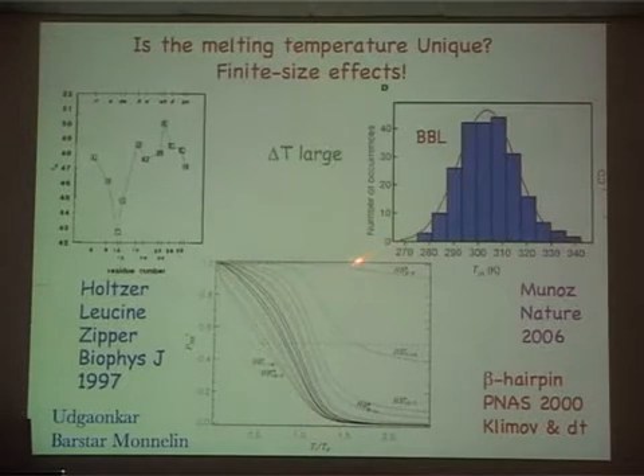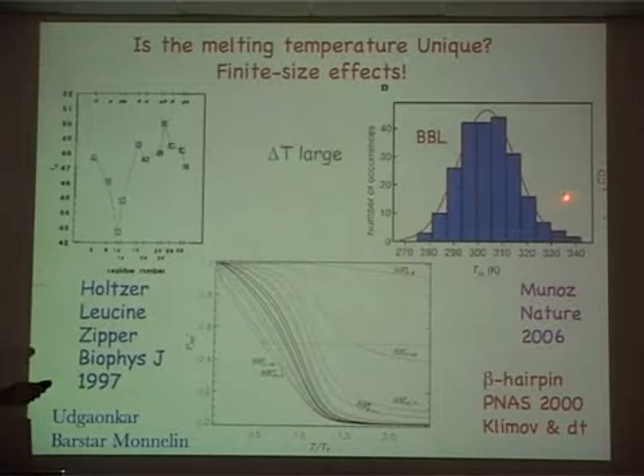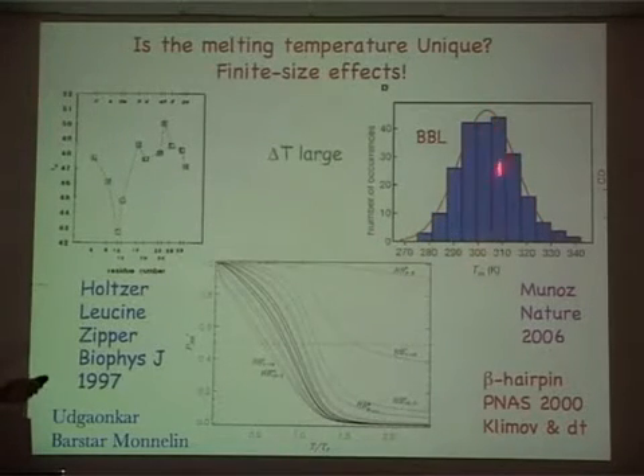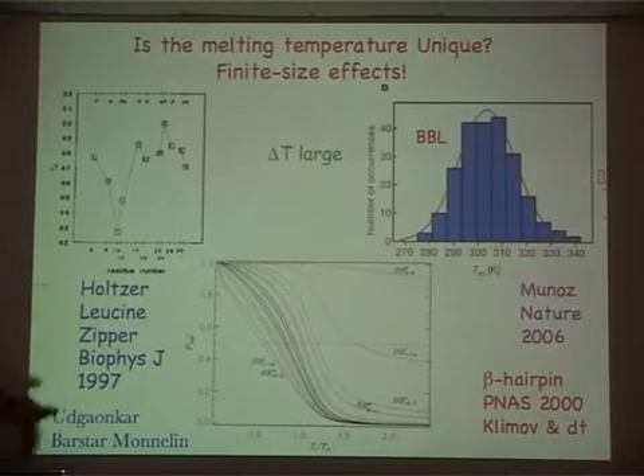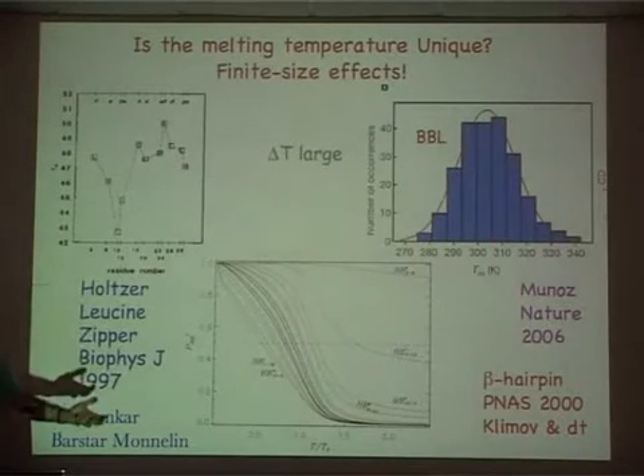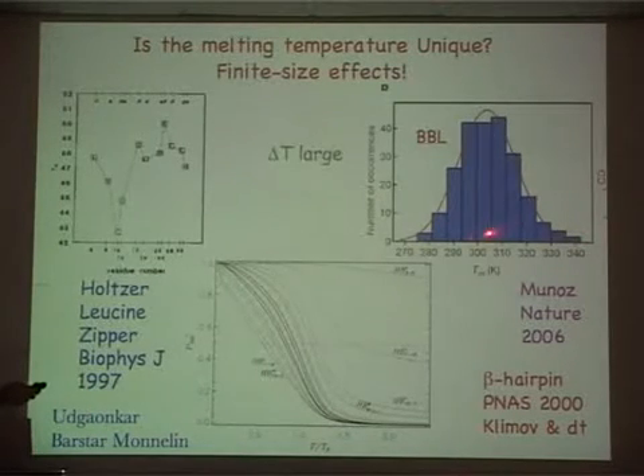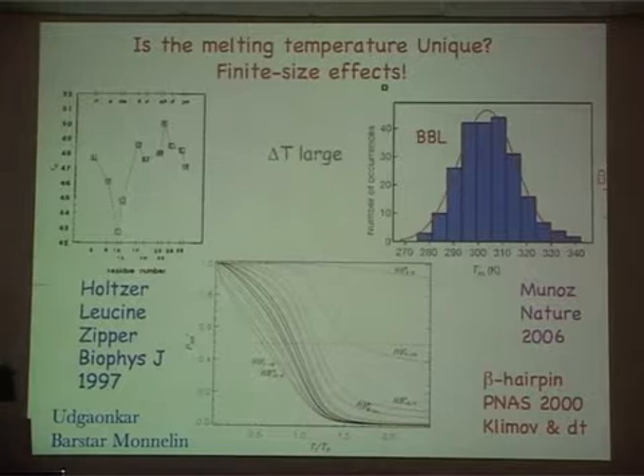Victor Munoz and my colleague David Fushman did an experiment which is really a super generalization of the experiment of the BBL. They sat in on about 100 or so protons that are present in BBL, and calculated the ordering temperature in much the same way Holtzer did in 1997, as a function of temperature. This is a distribution of melting temperatures, and you find that this is about 300 something. There is a melting temperature that you would report if it were just one melting temperature, but there's a large dispersion in this. And then they went on to make some deal about that. And this is really a finite size consequence.